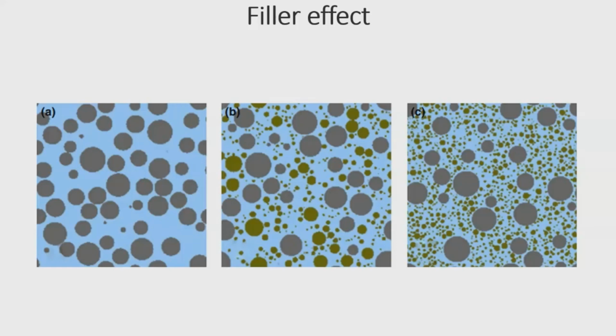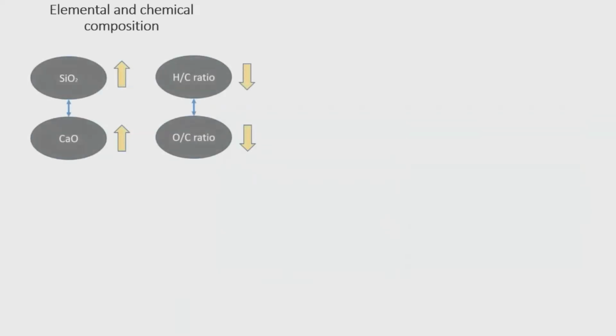CSH gels or Portlandite, CH, among other hydration products. This is where elemental and chemical composition are important, because we are looking for high contents of silicon dioxide and calcium oxides. This is mainly because these two oxides help to determine if a material has potential as a pozzolanic material or a latent hydraulic material. Otherwise, it might as well act as an inert filler.